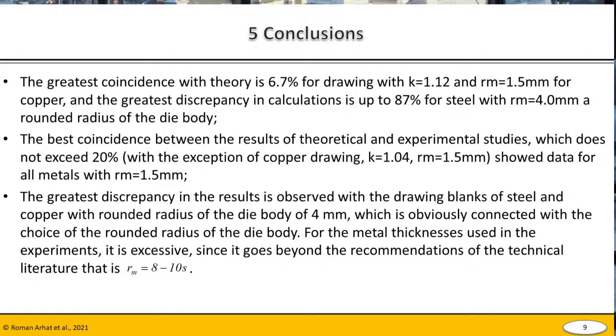The discrepancy between the results of experimental studies and calculated data can in general be explained by the imperfection of the mathematical model, when not all factors of a constructive and technological nature are taken into account, as well as by hardening of the metal during plastic deformation. In particular, the greatest discrepancy is observed when drawing blanks of steel and copper with a rounded radius of the die body of 4 millimeters, which is obviously connected with the choice of the rounded radius of the die body